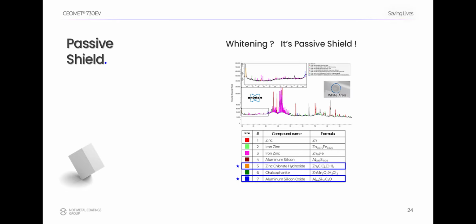These include zinc chloride hydroxide-based phases, similar to simonkolleite. Simonkolleite is known as one of the most stable zinc-based compounds. GeoMet 730EV also forms aluminum-silicon oxygen-based phases, similar to aluminosilicate or ceramic-type compounds. Together, these stable compounds create a new passive anti-corrosion layer on the surface. The key point is this: whitening is not a defect. In the GeoMet system, whitening is a passive shield.